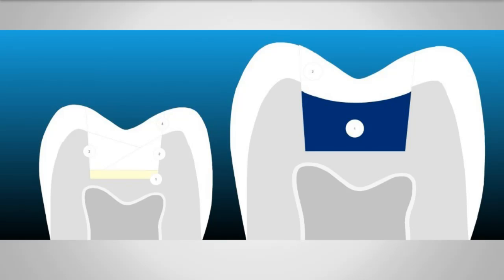What we can do is, in the dark blue here, fill the bulk of the cavity with SDR, and then we can just cap the SDR material with any kind of nanohybrid, hybrid, microhybrid type composite that is suitable for posterior use. So SDR, although it appears to be a flowable type composite, and it's a flowable composite, it's not used in the same way that a flowable composite would typically be used. The volumetric shrinkage of a flowable composite is 6% or more. For SDR, less than half of that. So this is actually a bulk fill composite.